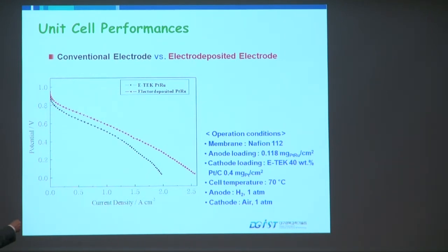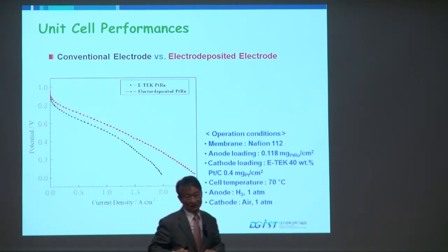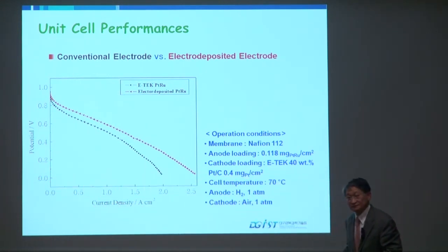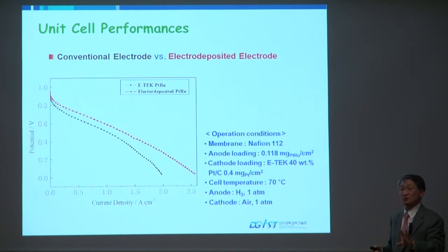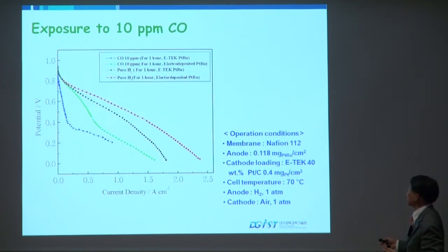The red electrodeposited platinum-ruthenium has 0.1 milligram platinum-ruthenium per square centimeter, which is pretty low. And as you can see, at the same potential, the current increased more than 35%. So that's one of the examples of what we did.